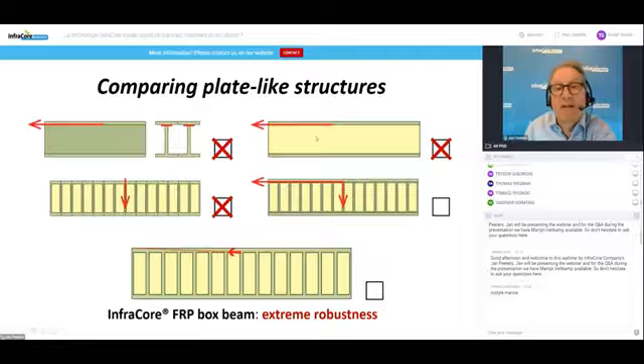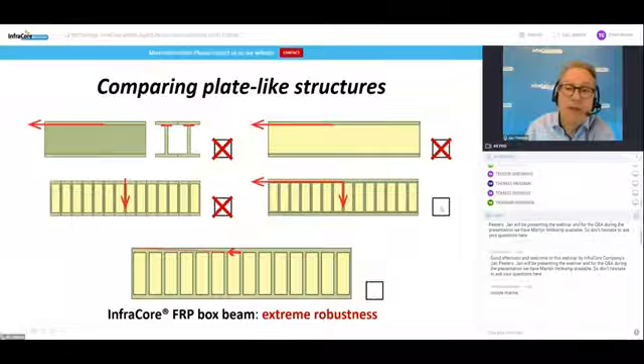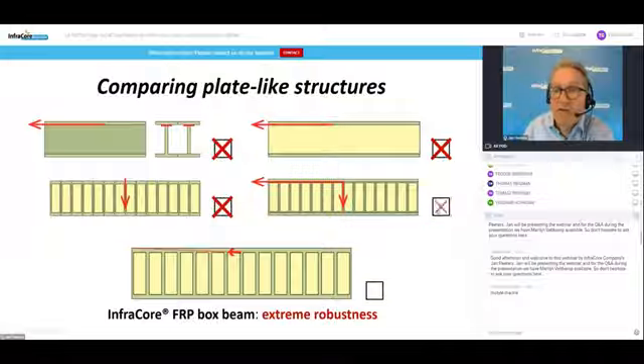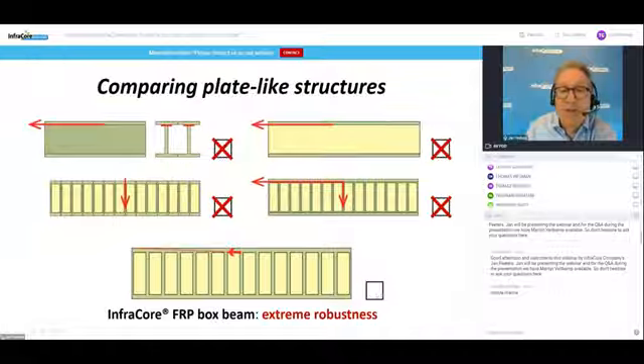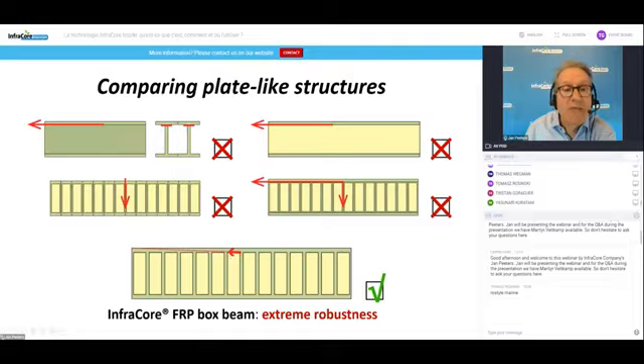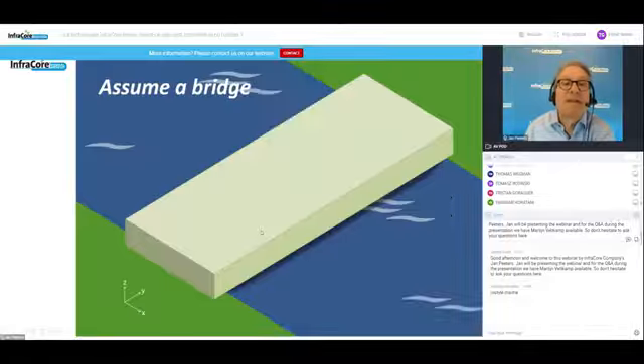You can combine a classic sandwich with a multi-beam, get a combination, but actually what you do, you combine two fracture modes. So that is not a solution. We have a solution in which we made a box beam, InfraCore box beam, in which you can get damage, but you will not be able to take away material from your bridge. So the load carrying capacity remains intact.